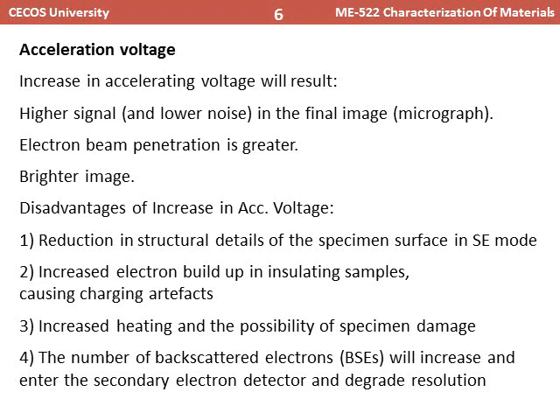The fourth disadvantage of increasing accelerating voltage is that the number of backscattered electrons will definitely increase, because as you can imagine, high energy electrons will penetrate to greater depth of the sample, so more backscattered electrons will be generated, and these backscattered electrons may reach the secondary electron detector. If the chances of backscattered electrons reaching the secondary electron detector increase, then the resolution you get from the secondary electron image will be blurred, or you are compromising the secondary electron image formation.